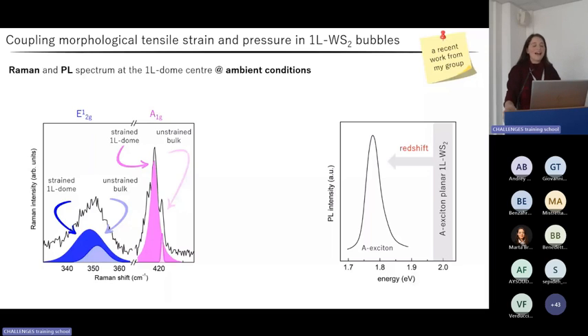Energy. Ah, sorry. It's very low because it is acquired at the dome center. And at the dome center, the monolayer is strained biaxially and in plane. And so you see this great red shift compared with the standard condition.